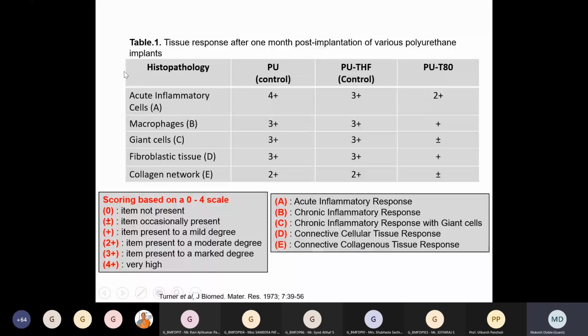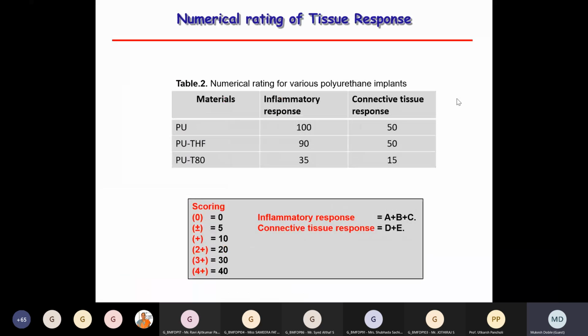So we tried to semi-quantitate this based on the histopathology studies. We looked at the different types of cells that are formed on the unmodified material and the modified material, and we tried to semi-quantitate based on the acute inflammatory cells, macrophages, giant cells, fibroblast tissues, collagen networks, and we tried to give some numbers and compare the unmodified material, which we call control, and the modified material, which is our test material. When we keep the unmodified material's inflammatory response as 100, we see that once we modify the surface with our technique, we are able to reduce the inflammatory response to almost 1/3. As you can see, the connective tissue response also could be reduced to 1/3 here. Okay, so we are able to achieve both.